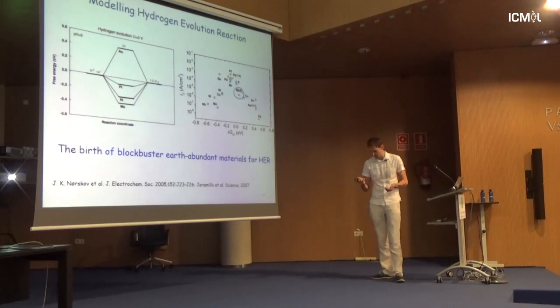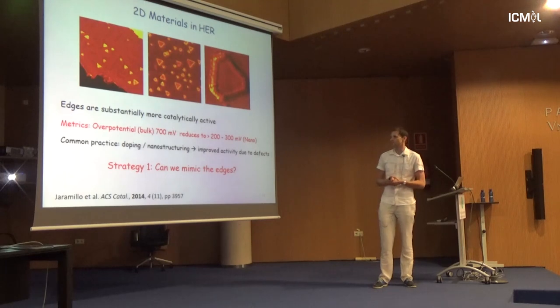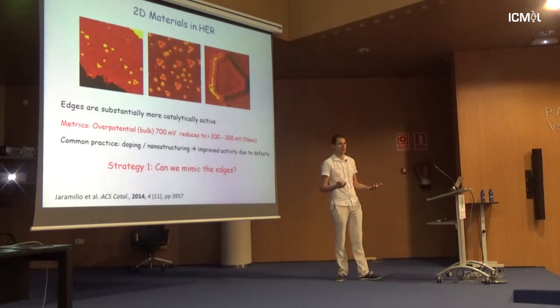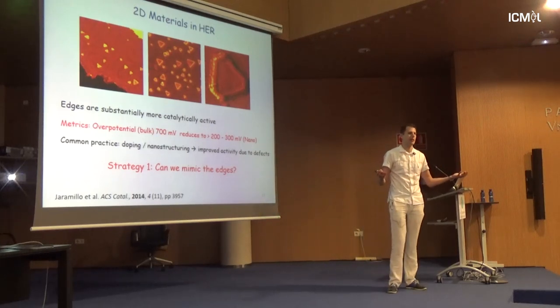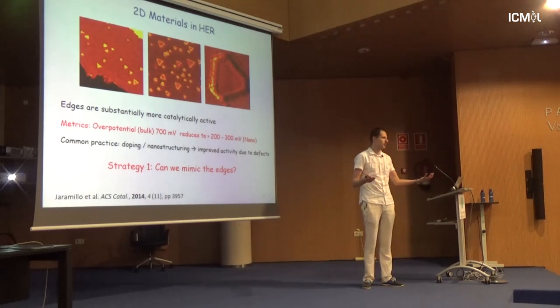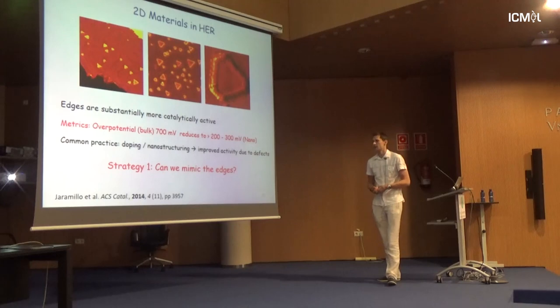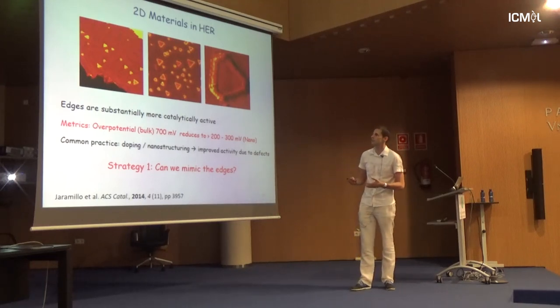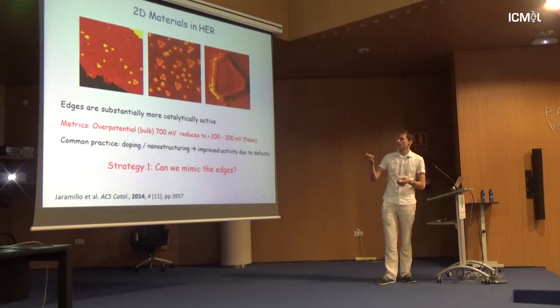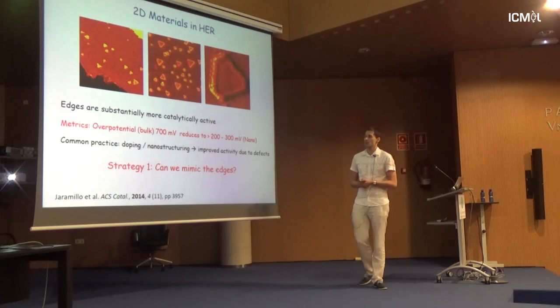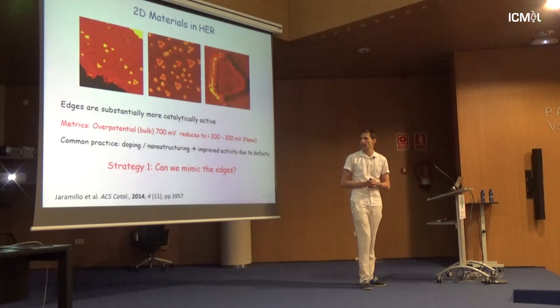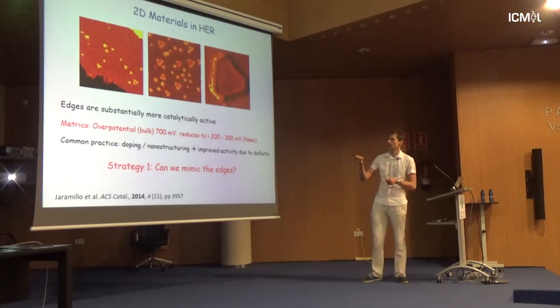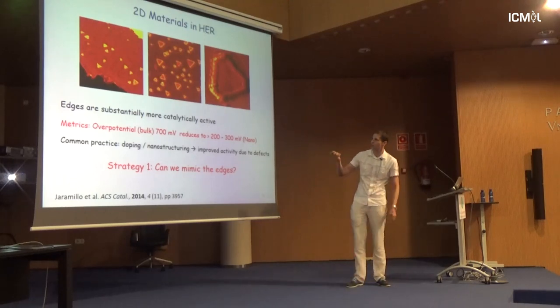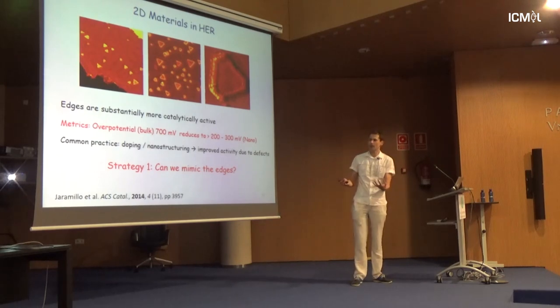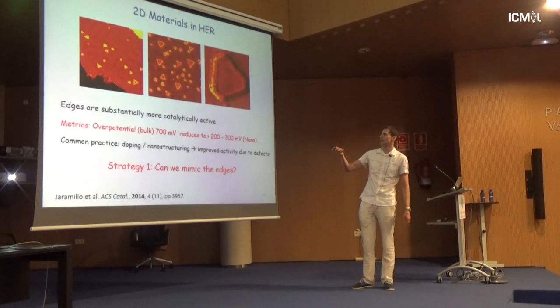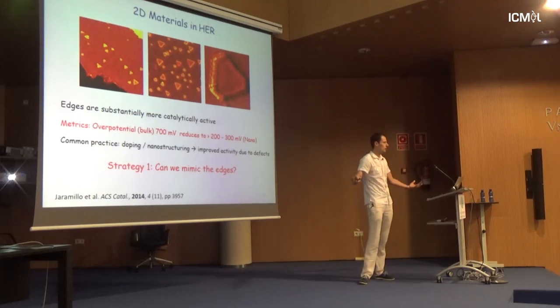And from this perspective, you have some sort of benchmark. So what was very interesting, in short, about 2D materials in general: as we know, 2D materials are very anisotropic. So you have edges, and you have terrace sites. And at that time, the Jaramillo group in particular took STM images. They just deposited molybdenum sulfide nanoflakes, so crystals, and they took a range of STM images, so you can calculate very exactly how much edge you have, and then compare with the surface. And then you can grow small, medium, large, and very large sizes. And then you compare what's going to happen.